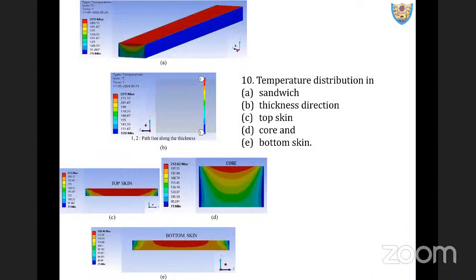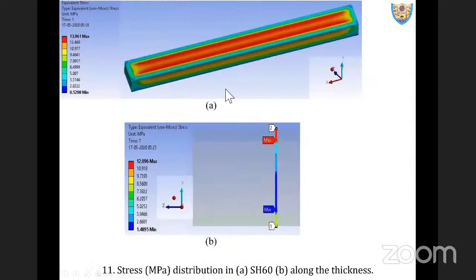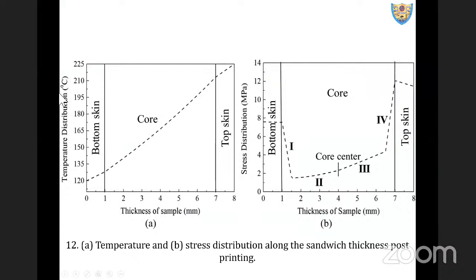Then, as I mentioned earlier, we did the finite element simulation, and the sole purpose of doing this simulation was to understand the residual stresses in the system, especially at the skin and core interface. It's a simple one. We found out different stress distributions across the thickness, and most importantly, we wanted to know the temperature and the stress distribution in the sandwich which is being printed.